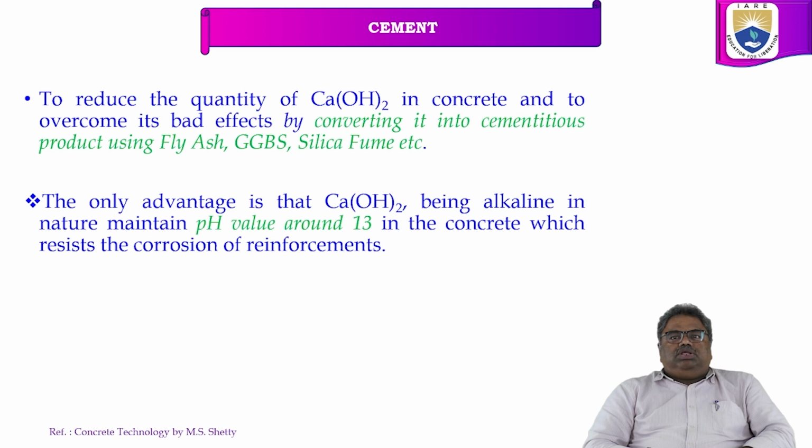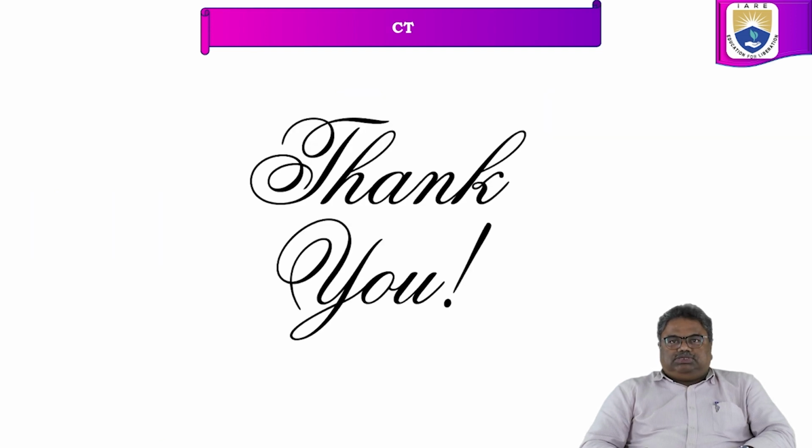The only advantage of calcium hydroxide is being alkaline in nature and maintaining the pH value at around 13 in the concrete, which resists the corrosion in the reinforcement. This is the only advantage of calcium hydroxide.